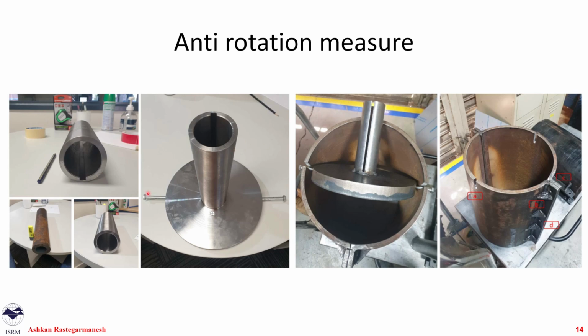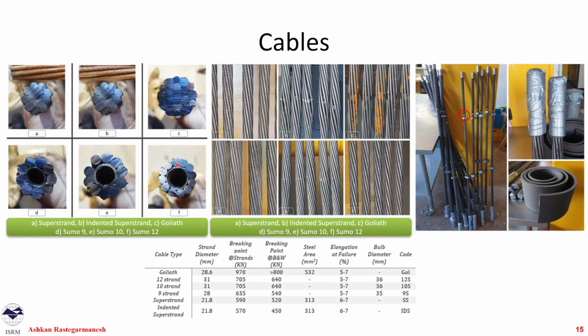And this was the anti-rotation plate that we ended up with, which is a much more robust way of doing it. And on the right, we see the picture of our external confinement. The cables that we used throughout this study, we used 6 cables. All of them were provided by Jennmar, one of the biggest providers of cables and rock bolts in Australia. In this table, we see the details of them, the diameter of them, and the breaking point load at the strand and barrel and wedge.